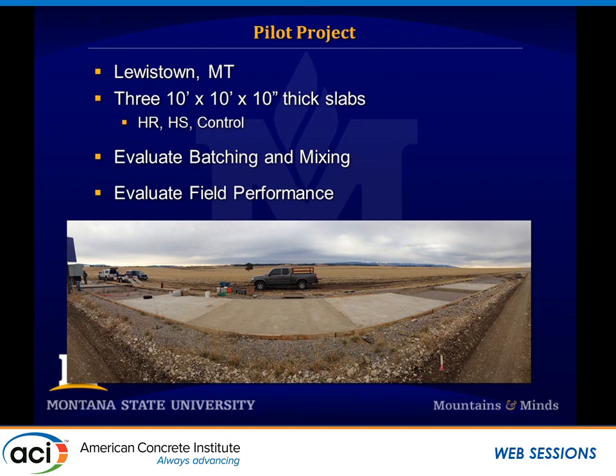Up there we made 3 10-foot by 10-foot by 10-inch thick slabs. If you notice, there's more than 3 slabs here. There's a whole section of slabs. This is on an approach road that gets quite a bit of traffic in and out of a rock quarry in Lewistown, Montana. The empty spots right here is where we put our RAP pads. The rest of these are some other recycled material concretes that we're using, involving fly ash and pulverized glass as the aggregate. So those are sitting on this test slab in Lewistown, Montana as well.